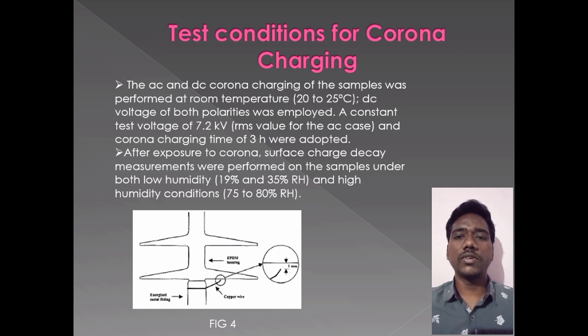Now I am going to explain about the test conditions. The test conditions for the corona charging experiment are: the AC and DC corona charging of the samples was performed at room temperature, that is 20 to 25 degrees Celsius. The DC voltage of both polarities was employed. A constant test voltage of 7.2 kV and corona charging time of 3 hours were adopted. The distance between the point electrode and the sample surface was the same for all samples.